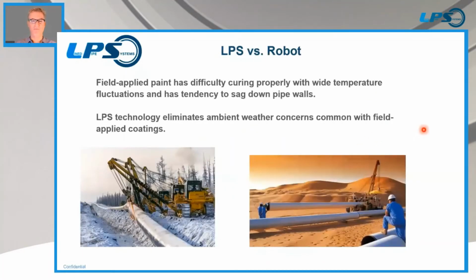So another big problem with robots is it's a field applied coating. Anybody that's been in the coatings industry knows that it's much easier to apply coatings in a controlled environment, a shop setting, and perform quality control. Whereas anytime you're in the field, there's unpredictability. Whenever there's a wide temperature fluctuation during a day, the cure times can be greatly affected. They will adjust the cure time of their paint based on the temperatures, but in the morning it can be cold, middle of the day it can be very hot, and the paint can actually have a tendency to sag down pipe walls as well, depending on temperatures of the steel. So whenever you can avoid applying coatings in the field, generally that's done in industry. And with the LPS system, obviously it completely eliminates that problem. When the rings and sleeves arrive at the job site, they're cured, quality controlled, and ready to go.